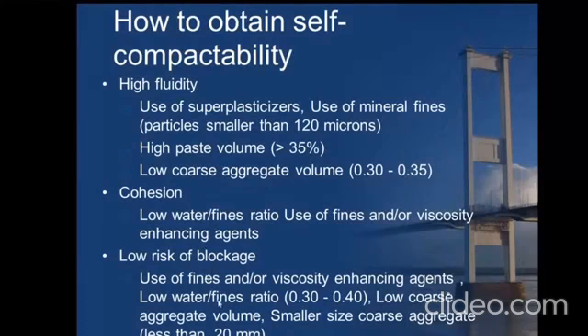So here we don't say it as cement alone, because cement is not the only binding material that is used. I told you the paste volume consists of a lot of mineral admixtures that go into the concrete. So here generally we say it is water fines ratio rather than water cement ratio. So 0.3 is nominal, but 0.4 is a little bit high. But in terms of more filler effects, then we go for it, because when more fines are added into concrete, it makes the concrete very sticky. So in that case, we are supposed to go with a higher water cement ratio.